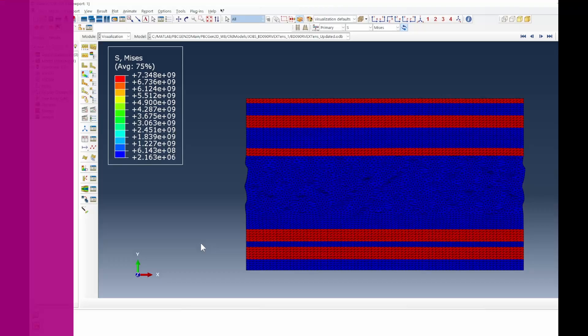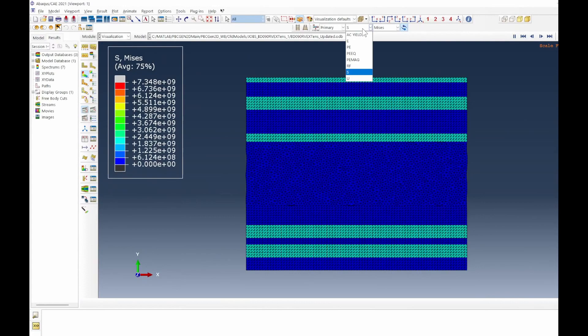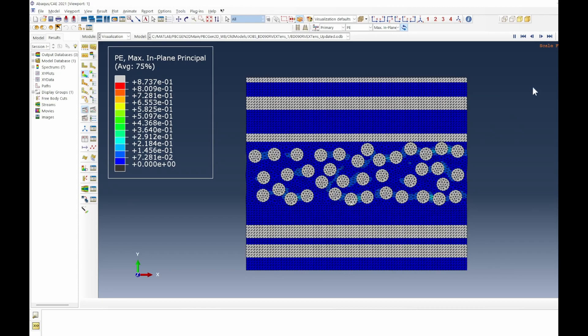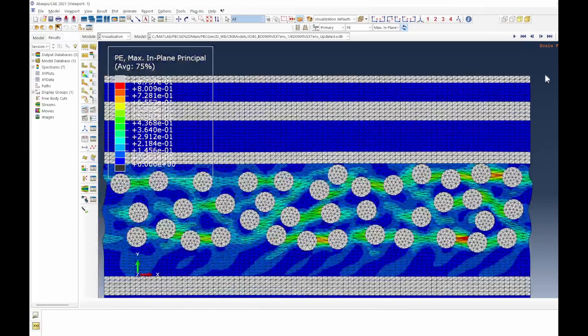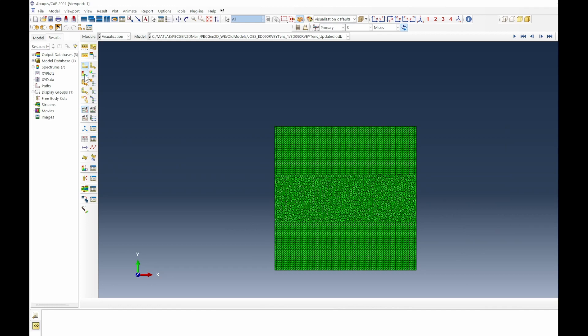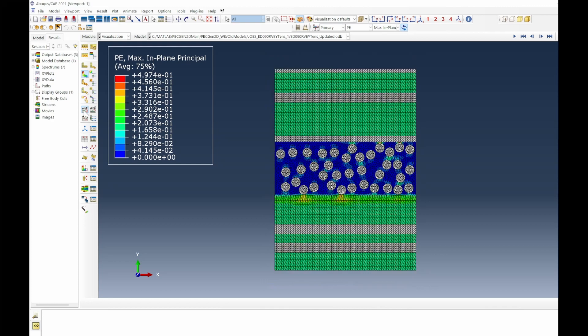The simulation result for the X-tensile case is shown and animated. Switching to plastic strain, we see a clear region with the fiber-dominated section, the matrix-dominated section, and the fibers. The periodicity is visible at the edges. Looking at mean stress, most stress is taken by fibers oriented in that direction. The Y-tensile case shows a similar scenario — fibers taking most of the load. The central region shows the 90-degree fiber, which is a weak zone as the structure is pulled in the y-direction.